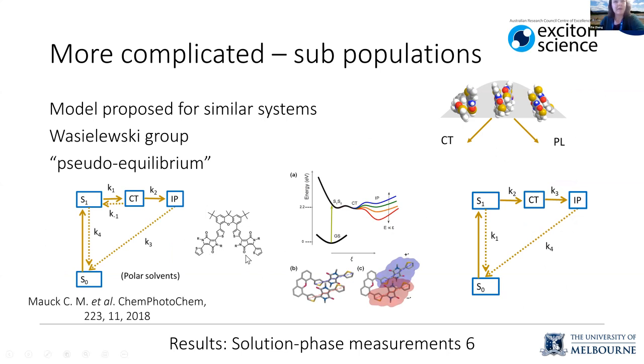What other groups have explained it by is, so here's an example where there's a similar dimer, but where it's fixed into a coplanar configuration. So the two chromophores are coplanar with each other. They saw similar behavior, but they explained it by having a kind of pseudo equilibrium between the excited state and the charge transfer state. So that you can go along this charge transfer pathway, but you can also go back to the first excited singlet state and fluoresce. But if this were the case, then we would see long-lived fluorescence. We would see fluorescence that was longer than the monomer alone, which is called delayed fluorescence. And we don't see that. So I don't think that this model is correct in our system.